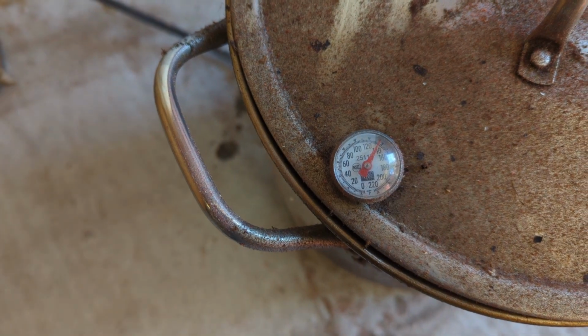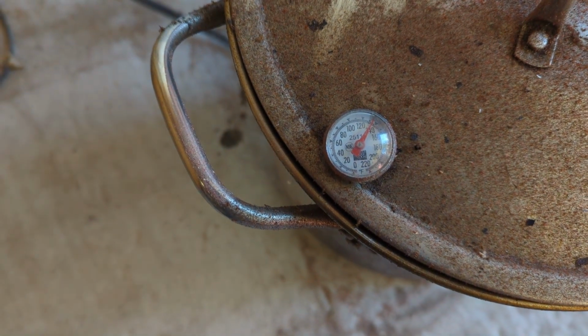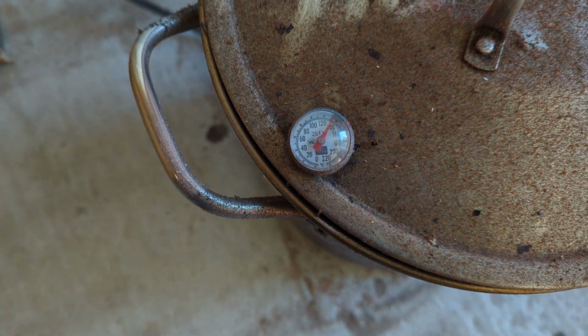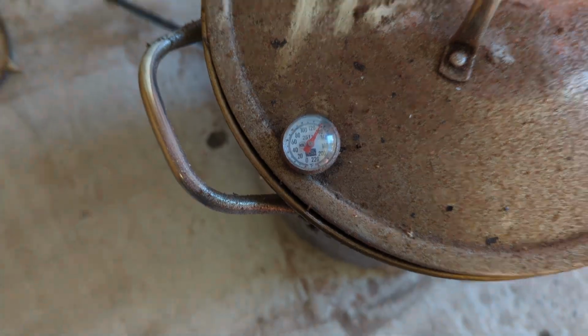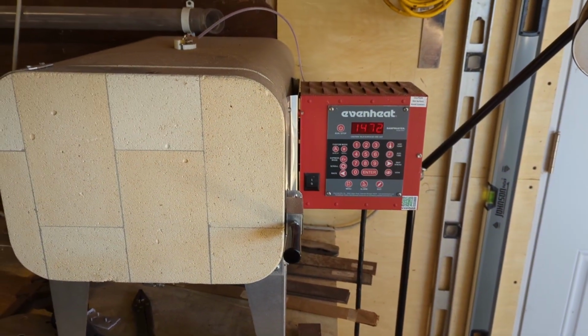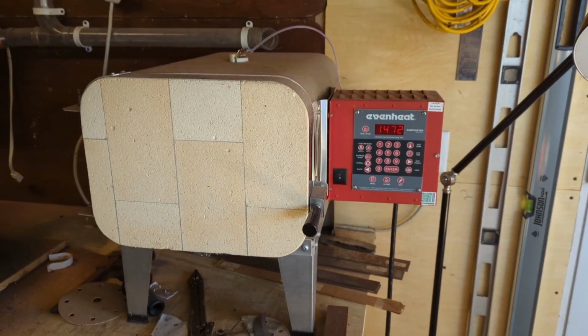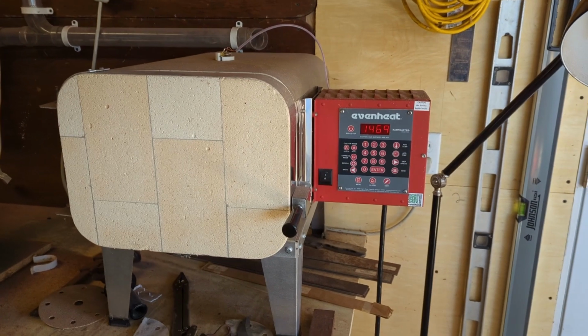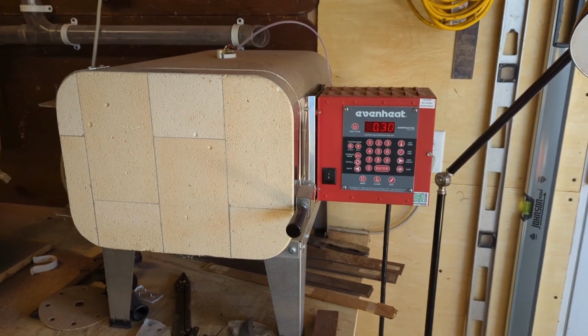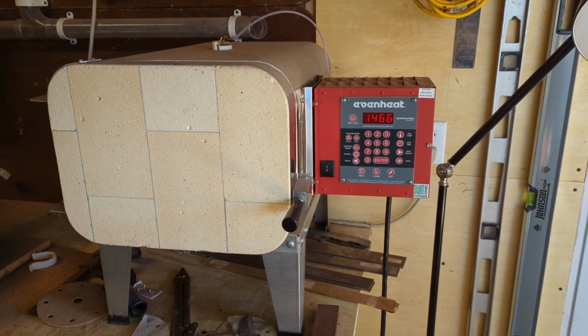And the oil is up to temperature. It's close to 140 degrees. It's between 135 and 140 degrees, and I shut the burner off, and that'll be just perfect by the time the knives are finished in the kiln. You can hear it's beeping now. We reached temperature. Now we just have to wait. I have 30 minutes programmed in as a hold.